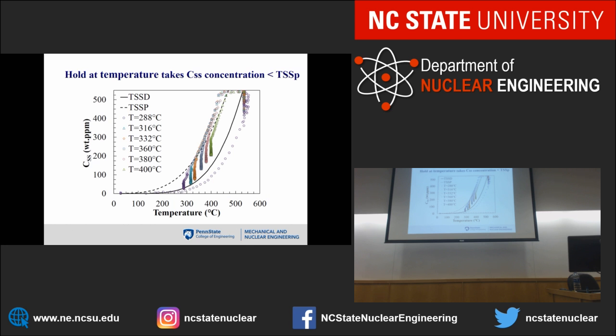Here's his data. So he took it up faster. So the thing was a little bit lower than that, but that doesn't really matter. It was all dissolved here. He comes here, and then he starts holding it at different temperatures, at 400, at 380, at 360, at 332, etc. And these are the data points. They all get down to the TSSD. They continue precipitating in the hysteresis region. They don't stop here. So this just controls nucleation, but this controls growth. And this indicates that the TSSD is a real thermodynamic limit and the TSSP is a kinetic limit.